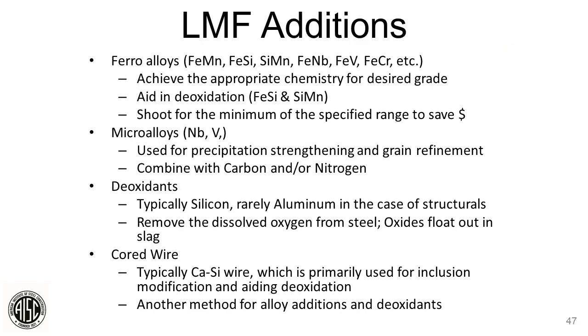Typically, silicon killed is what we primarily produce in the United States. Sometimes aluminum killed, but not as often. And we remove the dissolved oxygen from the steel. The oxides are lighter than the steel, and they float to the top during the stirring process. And we also add cored wire, typically calcium wire, and we use that for inclusion modification and aiding deoxidation. Again, silicon takes out oxygen, and the calcium wraps itself around the inclusions to minimize their detrimental effect when rolling. And it's another method for alloy additions and deoxidants if we need to do that. Next slide, please.